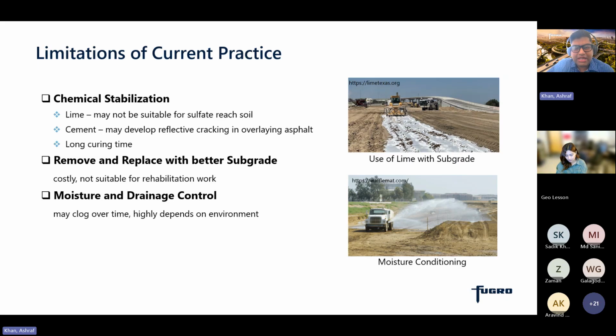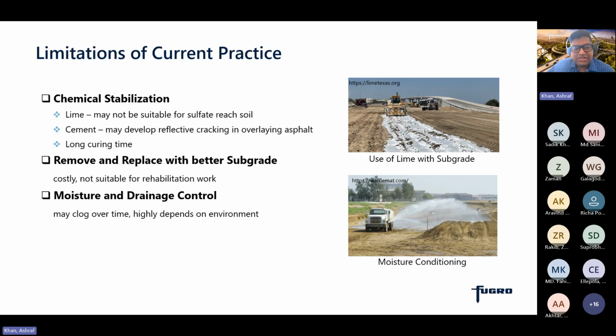Another solution people use is moisture conditioning. How it works is, if you add water in such a way that during the dry season it can retain the moisture, but this is weather dependent. And if you have a very dry summer, water can be taken out, and the reduction in moisture will lead to the shrinkage, cracking, and expansion of soil in the next rainy season. So this kind of solution has some limitation, which justifies the need for a more resilient and sustainable method.